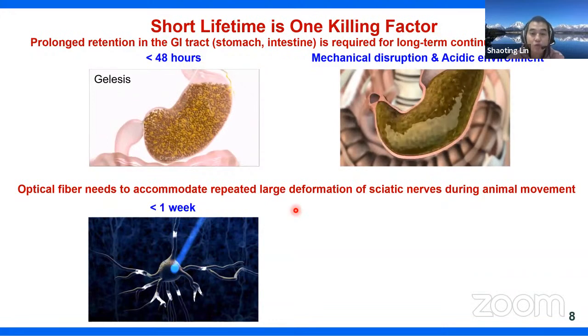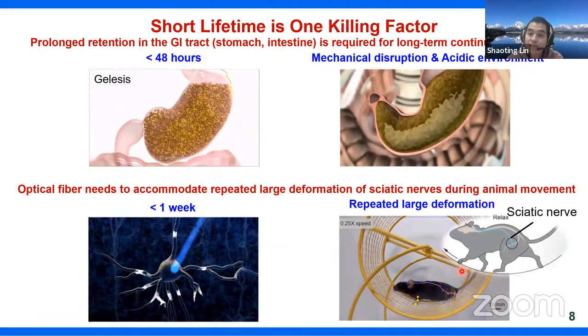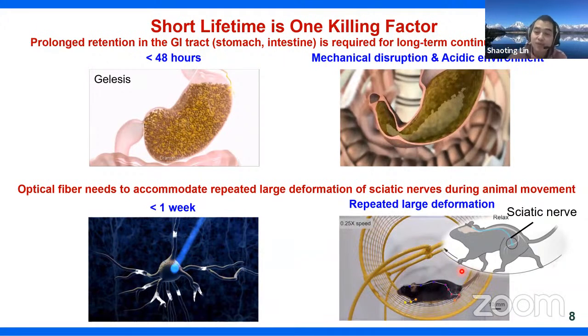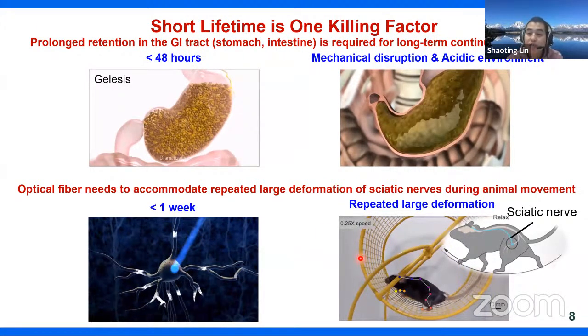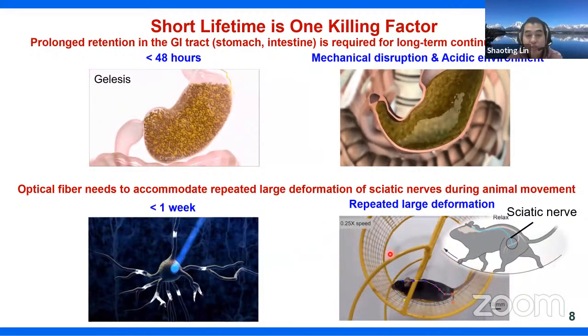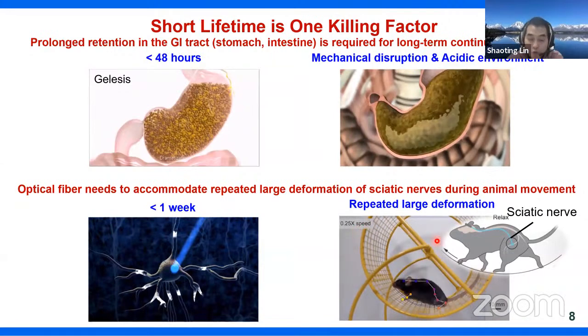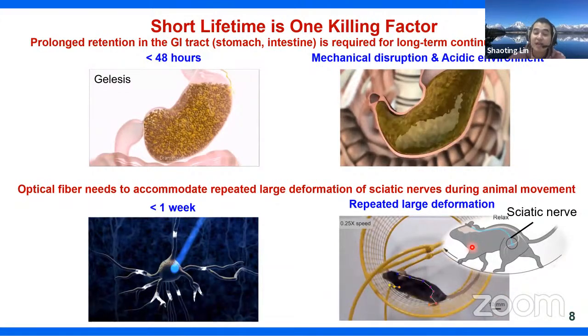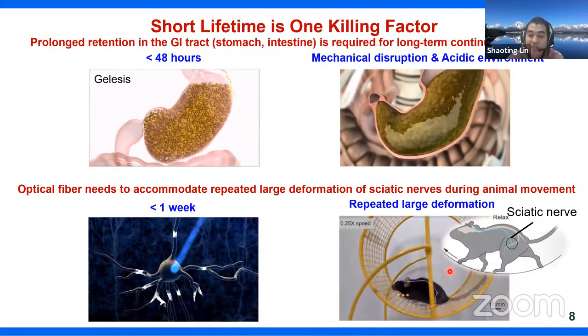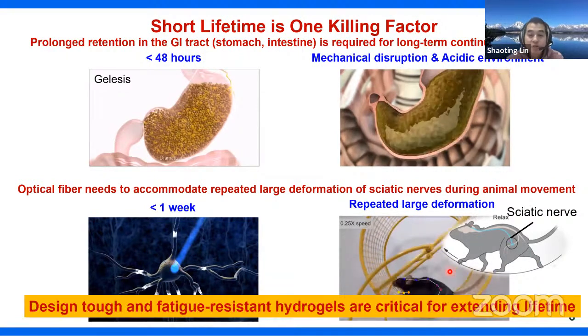The second example is the optical fiber, which has been actively used as an effective tool for light delivery targeting deep tissues. But unlike the neuron probe, the sciatic nerve actively experiences repeated large deformation, especially when the animal is actively moving. And this repeated large deformation will eventually induce mechanical failure of the fiber. The question is whether we can make the optical fiber more durable so that it can accommodate this large deformation of the sciatic nerve and achieve long-term light delivery in dynamic organs. So the message for this slide is that designing tough and fatigue-resistant hydrogels is critical for extending lifetime.